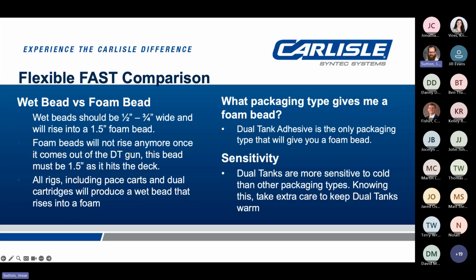In our specifications and a lot of our documentation, you'll see a wet bead versus a foam bead. The difference between the two: a wet bead is produced from any of those packaging types that I mentioned that use equipment to push it out. So your dual cartridges, your 50-gallon drums, and everything in between other than the dual tanks, all will produce a wet bead. We want to see that at about 1/2 inch to a 3/4 inch wide as it hits the deck. That's going to give us about a 1.5 inch wide foam bead at the end after it's risen.